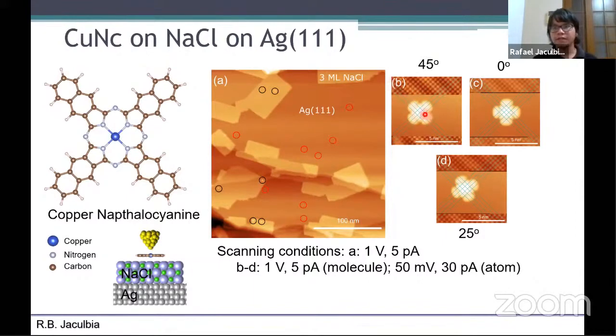So we found that the molecule can be present on the surface in three different configurations. It can be parallel to the chlorine axis, or perpendicular to the chlorine, or at some angle. But I found that of these species, the one I call the 45-degree molecule is the most abundant. So in this presentation in our work, we just focus on this molecule.